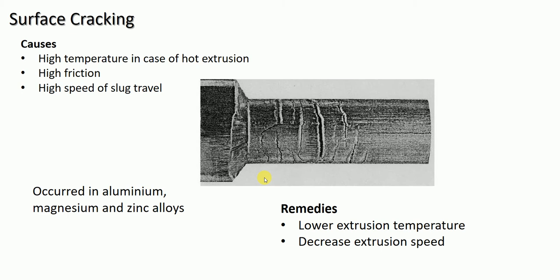The first defect is surface cracking. Here, this one is the extruded product. On this product we can see that a large number of cracks have developed on the surface — these are nothing but surface cracking. Surface cracking is developed because of high temperature in the hot extrusion process. If that temperature is excessively high, the formation of surface cracks takes place.